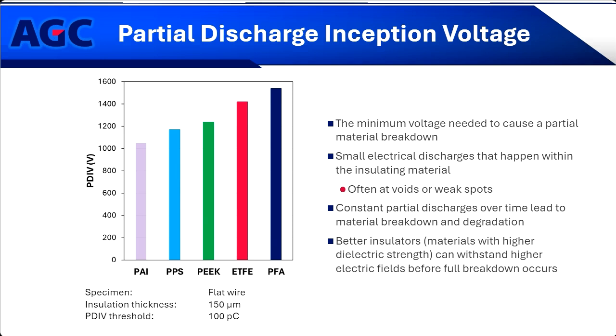The insulation thickness is incredibly important for this. As you get much thicker insulation, that's going to give you higher and higher voltage data, higher PDIVs. And the reason I say this is because it's really easy to look at a material specification or a technical data sheet and say, this company can get a PDIV of this number, this company doesn't get that high. It's really important to understand how those materials are tested and really make sure you're comparing them, as you would say, an apples to apples comparison.